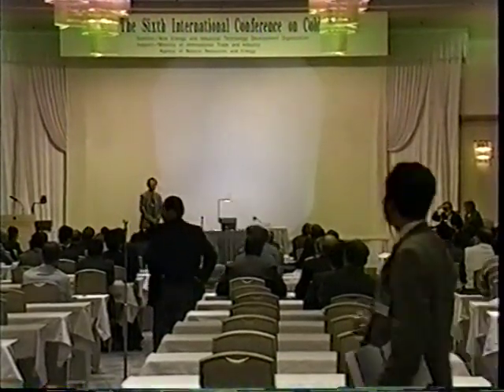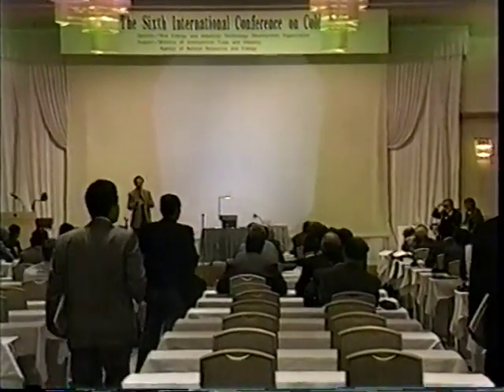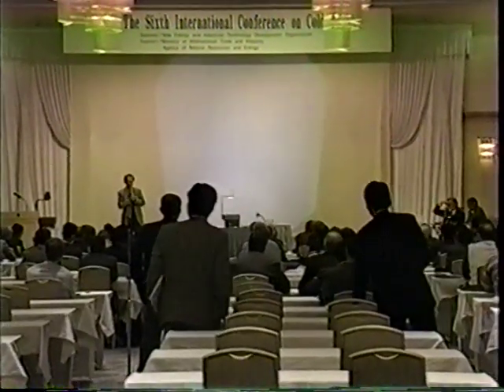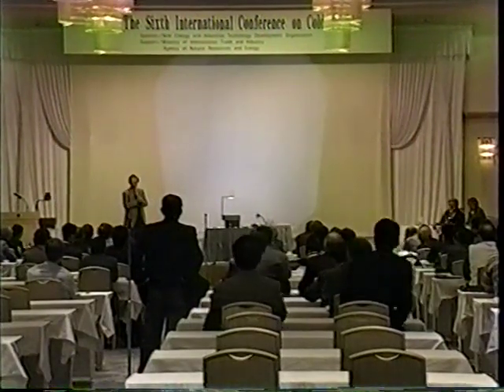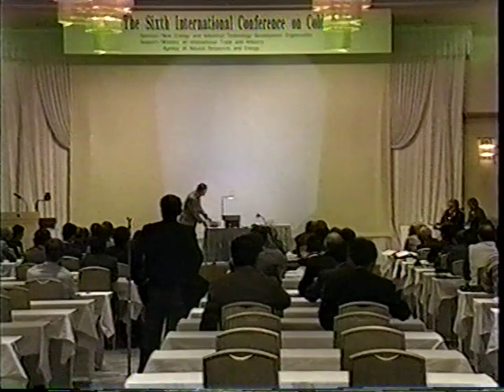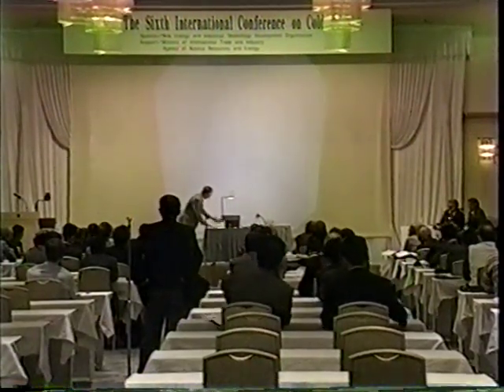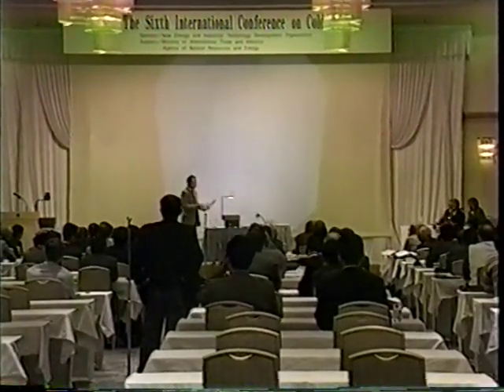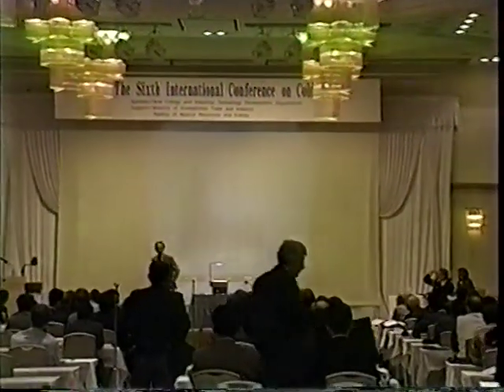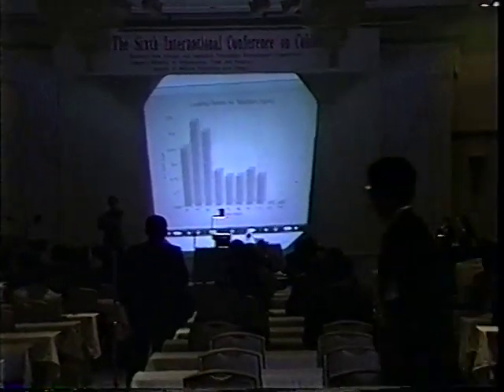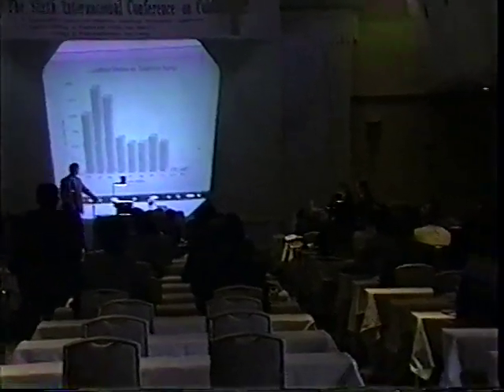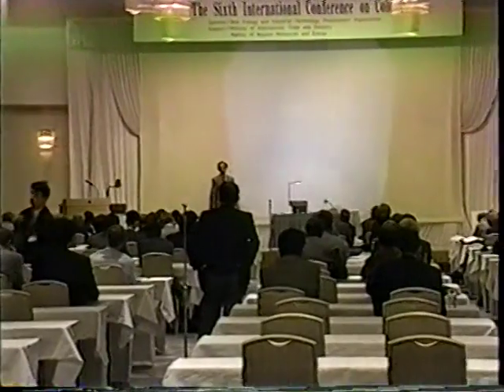Thank you, Mark. That is an interesting point. I had not the possibility to say that there are many electrochemical problems accompanying this material problem, because I have not enough time. For instance, this is the very funny effect of the solution aging on the loading. If we prepare the solution and we store it in a glass bottle, we have a chemical attack of the bottle, and then we have many impurities in the solution. And then we discovered that the optimum is after 1 month. Anyway, I know that there are very important electrochemical problems that are not easy to control. Thank you.